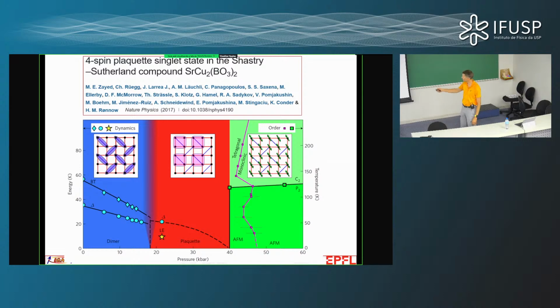In this work, we also found out that if you apply too much pressure, then you actually break the nice symmetry of the crystal. You get into a monoclinic phase, and you get an antiferromagnetic ordered state, which is less interesting from a quantum many-body perspective. Okay?